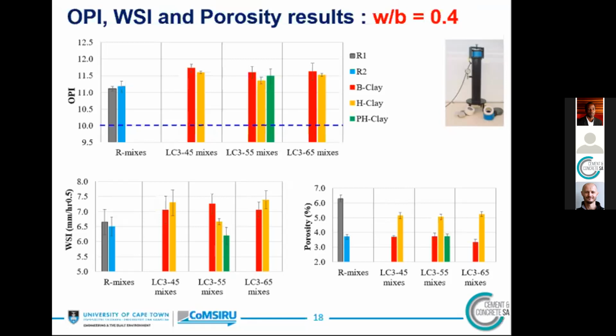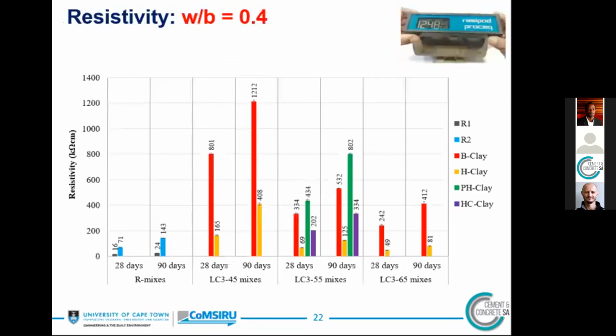Now, if you go to slide number 22, where you talk about resistivity, I'm just interested to know the size of your prism. I don't know whether it's a prism or a cylinder. It's a cylinder. What is the size of it? The height is 200. So if the height is 200, and for this Wenner probe the probe spacing is 50, you have 25 millimeters on either side, assuming you place the probe at the longitudinal center.